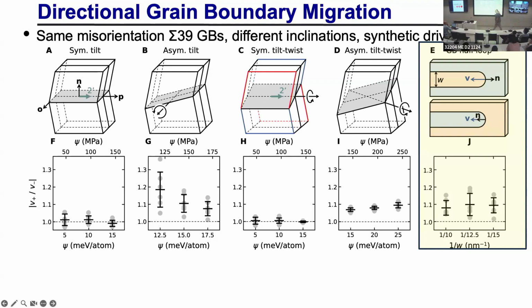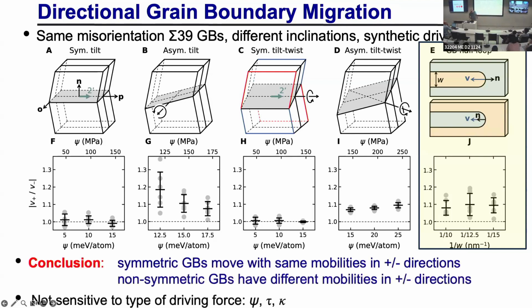Okay, so conclusions from this whole part. Symmetric grain boundaries move with the same mobilities in the plus or minus direction. Asymmetric and non-symmetric grain boundaries have different mobilities in the plus or minus direction. It's not sensitive to the type of driving force, the magnitude of the driving force, or which material it is. It only seems to be sensitive to the symmetry of the boundary. Okay? So let's take it apart and see if we can figure out why this is the case.